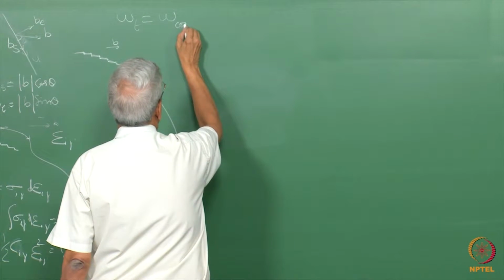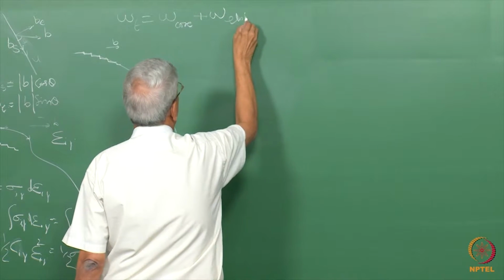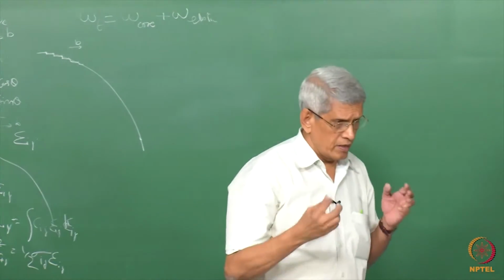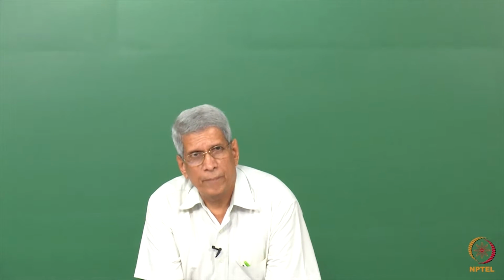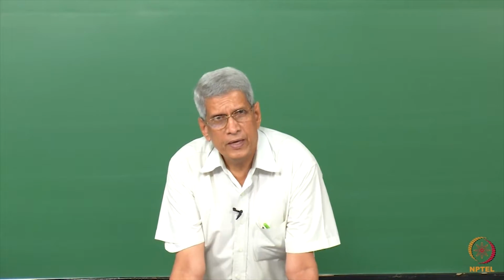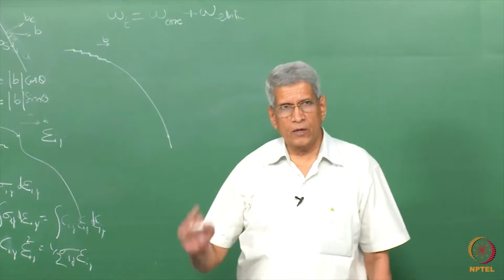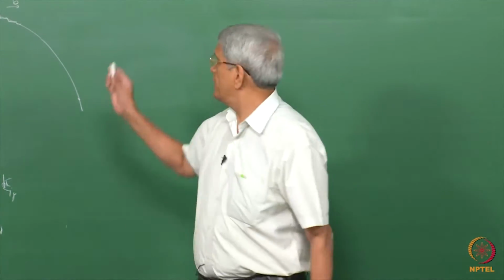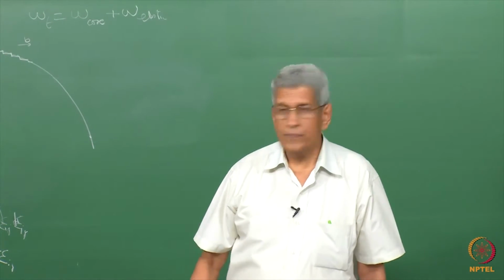the core energy, and the other is the elastic energy. Core is the region where we cannot apply Hooke's law. Linear elasticity theory cannot be applied. So the stress and strains which we had calculated are also outside of the core. This will give rise to the elastic displacement.